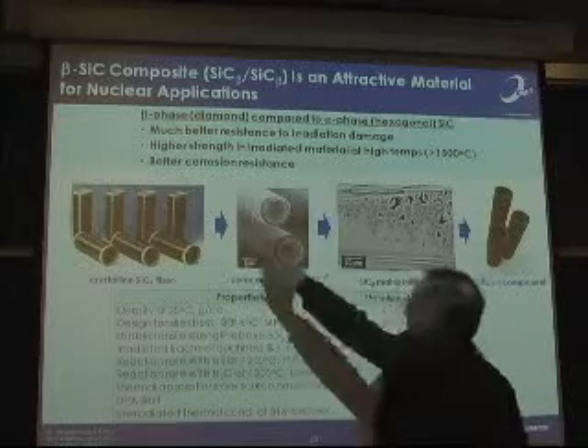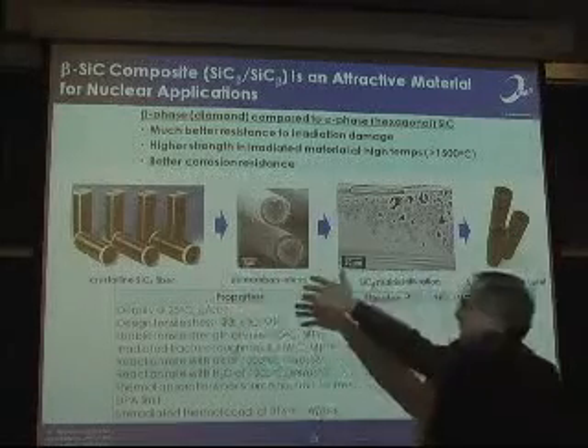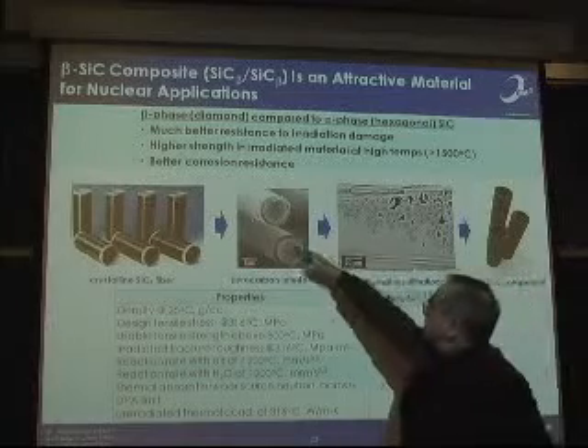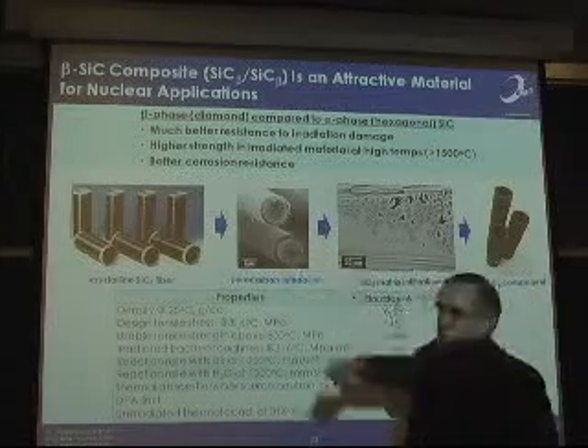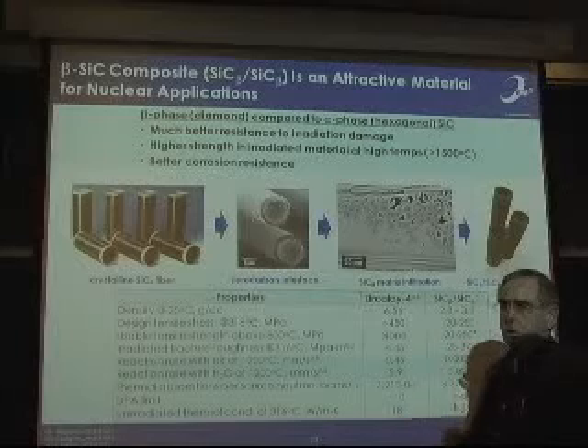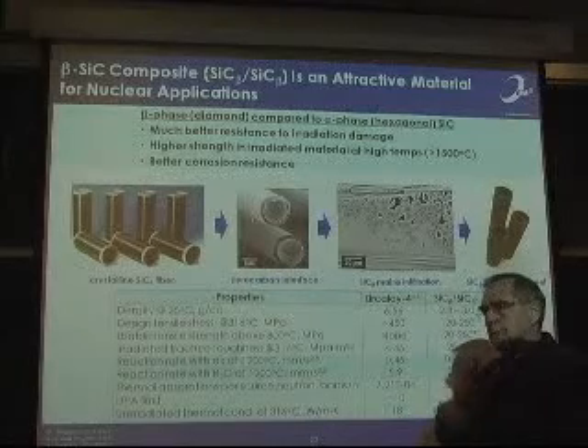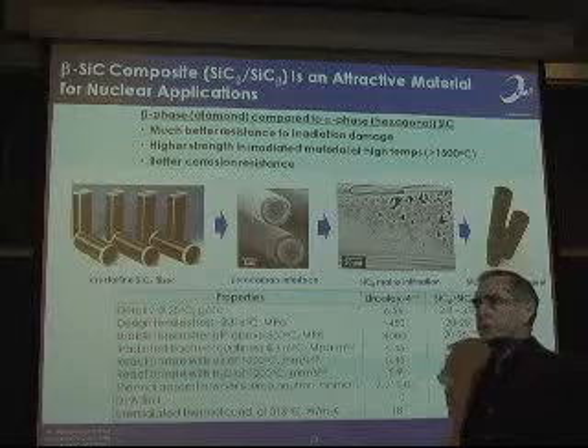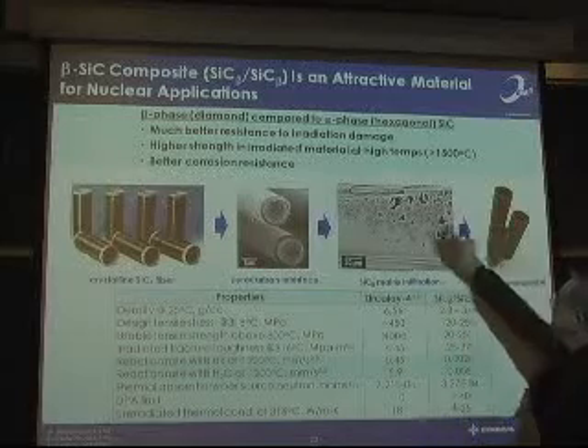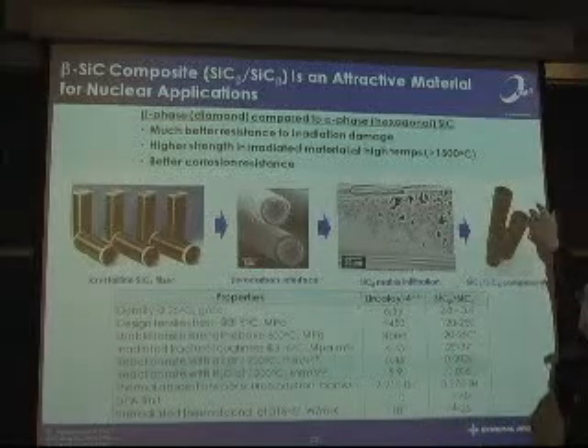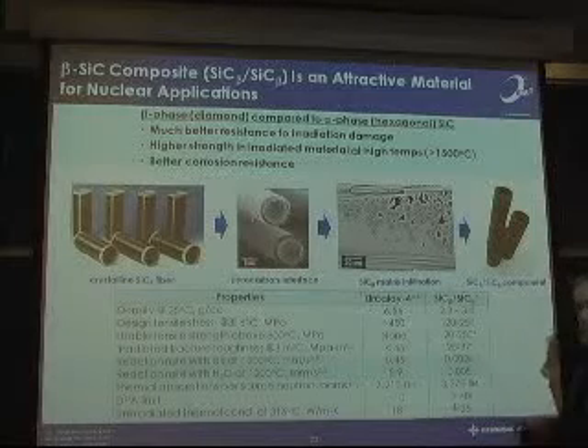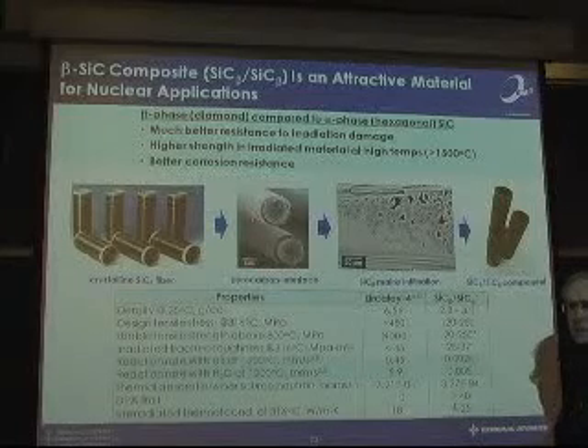Well, I mean, you make the composite by making a fiber preform. You do put a small layer of pyrocarbon around each fiber so that you get slip between the fiber and the matrix. That's very important in fracture toughness. Then you infiltrate it, and ultimately you make tubes. And we're making tubes. They're a little bit crude right now, but we're getting better at it.